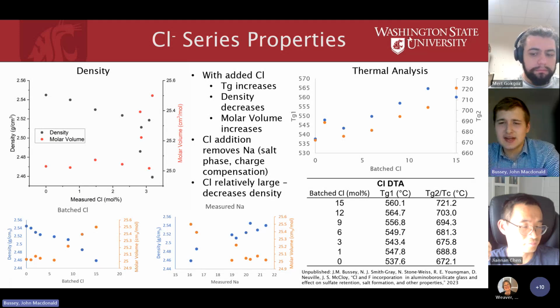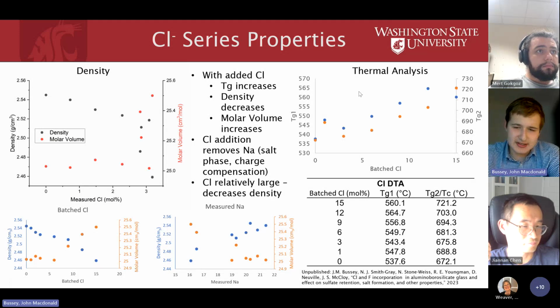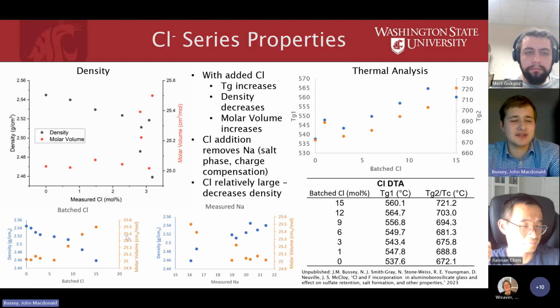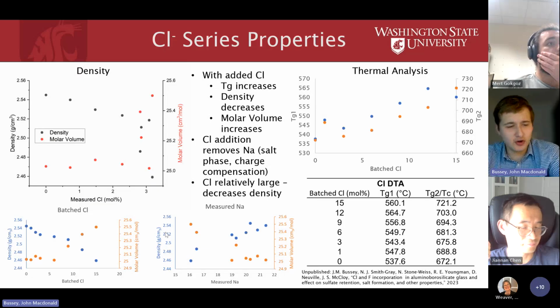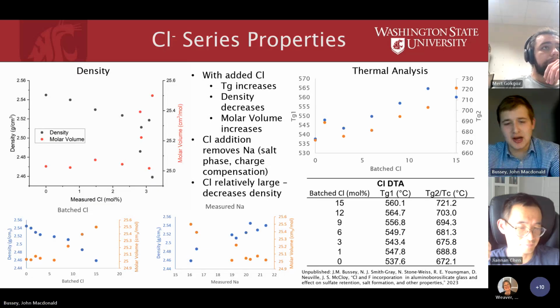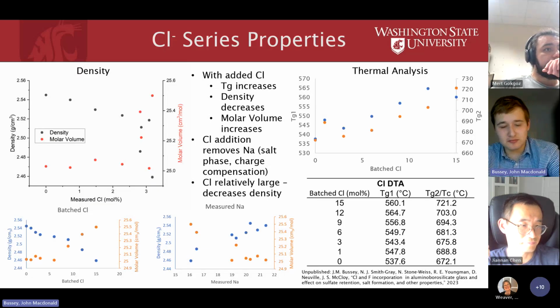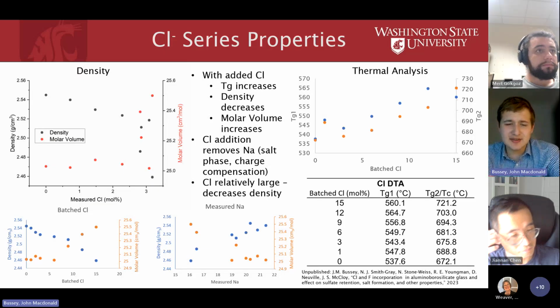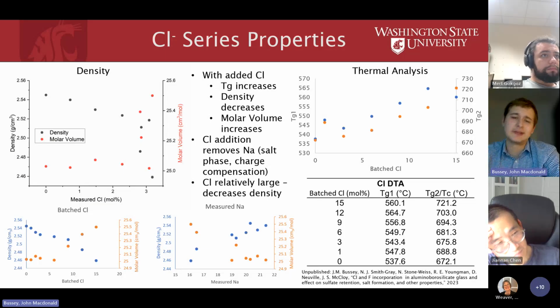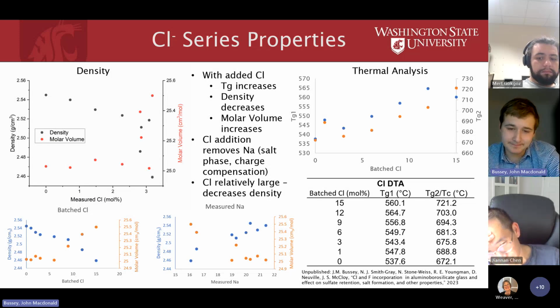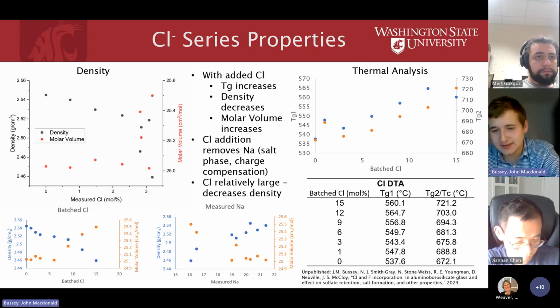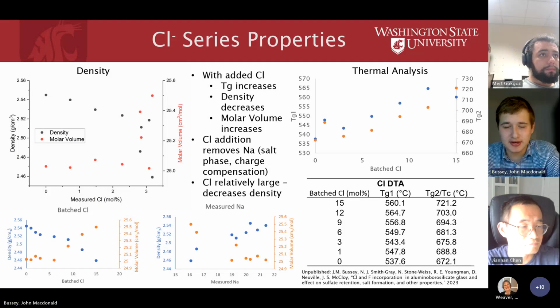This here is a variety of properties. So the density decreases and the glass transition temperature increases, and as we plot that against sodium and chlorine, we see that as you add more chlorine, the density goes down, and against sodium, the less sodium there is, the density also goes down. So again, what this tells us is that as you add chlorine, you remove sodium, and it goes into a salt phase. The sodium goes into the salt phase to charge compensate the chlorine coming in. So that's the primary story here.